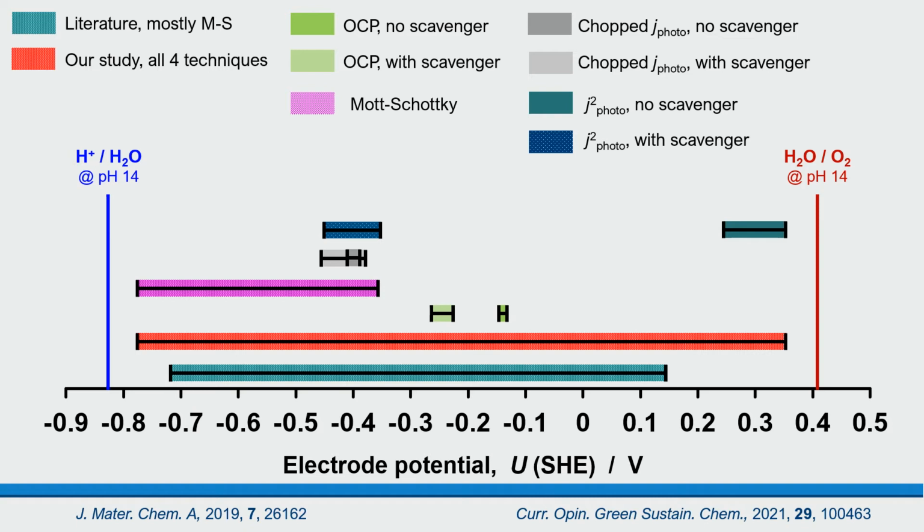So this has to be corrected for recombination and so on to back calculate the flat band potential value. But essentially the values are all over the place. And part of the reason is that the analysis of experimental data for flat band potential determination often excludes the contribution of the Helmholtz layer to the experimentally determined results.